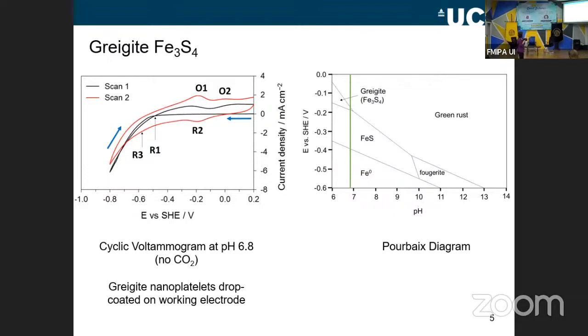As I do it, I measure the current. If a current flows, so if the value is not 0, it's telling me the reaction is taking place, okay? And if the current is a negative value, it tells me it's a reduction current. So what I want you to do is just look at the black line in this diagram. Ignore all of the red lines, just the black one. I'm going to start here and go along in this direction. As you can see, the line is flat. Nothing is happening, so no reaction is taking place. Then at point R1, I start to see a negative current flowing down here. That tells me that there is a reduction reaction taking place, so I'm reducing the greigite or something on my electrode surface.